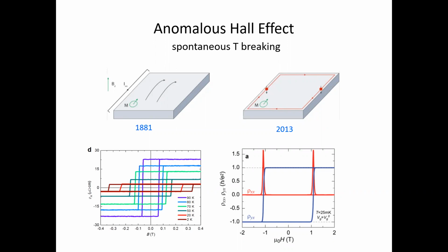For example, if you look at a material like iron, or in this case, a ferromagnetic Weyl metal, you see that at a low temperature, when the material becomes ferromagnetic, even at a zero applied external magnetic field, the Hall resistance becomes finite. And it shows hysteretic behavior, indicating that this transverse resistance has something to do with the spontaneous development of magnetization in the sample. So magnetization replaces the role of the external magnetic field.